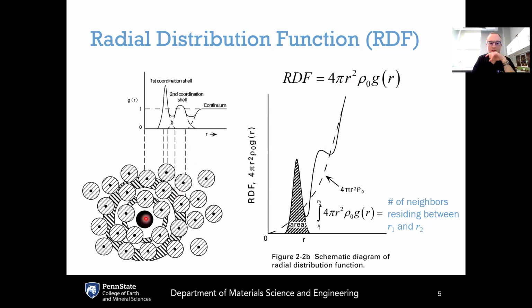So if you start at the central atom, which has r equals 0, and then expand out from there, these spheres, these shells, are expanding out radially, and the surface area of each one of those shells is given as 4 pi r squared. If you take that 4 pi r squared multiplied by the number density and then multiplied by the pair distribution function, the area of that would give you the number of atomic neighbors that reside between the two limits of the integral. So the radial distribution function, if we plot that, is going to have a lot of the same features as the pair distribution function, including being 0 at low values of r, having a first peak, followed by a trough, followed by a second less well-defined peak, followed by another trough, followed by complete randomization of the glass structure.